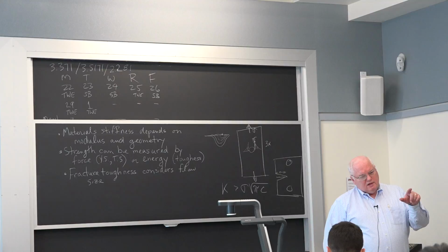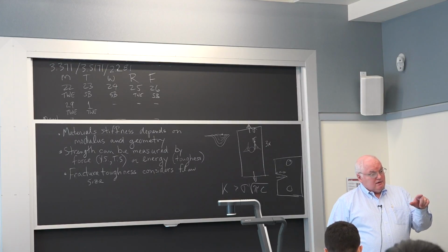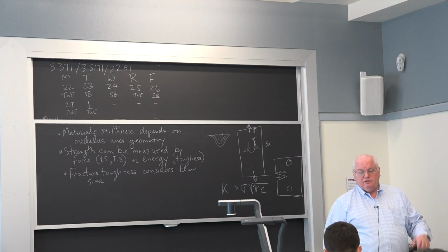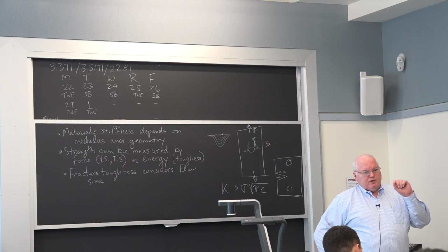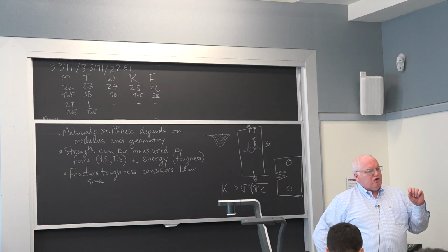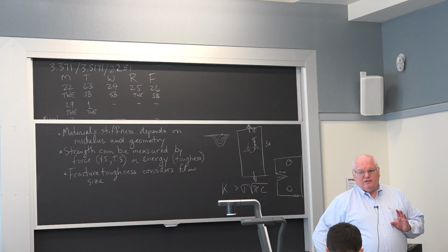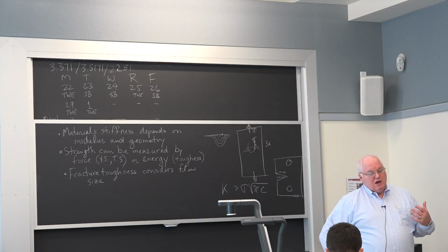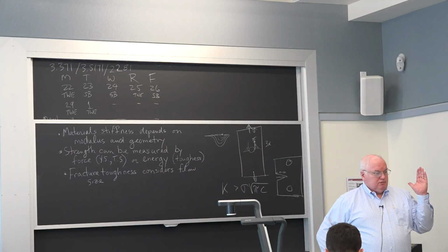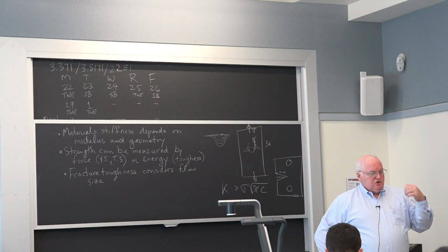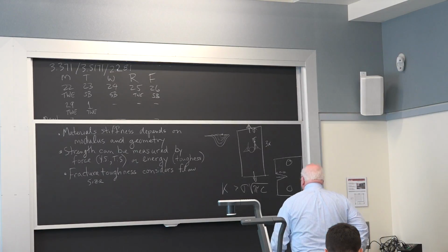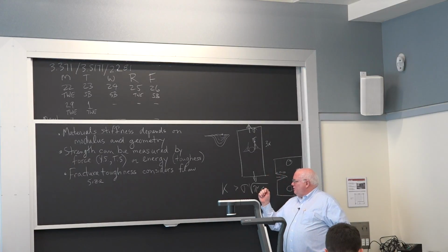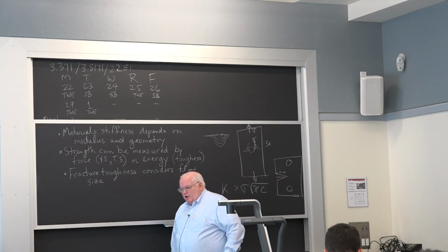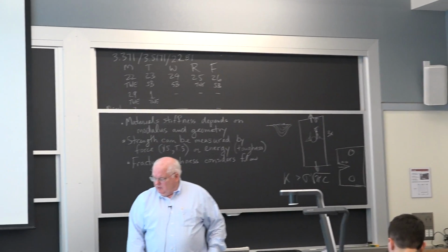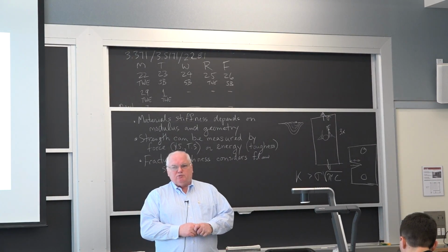And he found out, well, they already knew granite is a three-phase material. You can see white, black, and gray, 3 different crystal structures of 3 different minerals in granite. And what he found is that at the tip of the crack, you actually get little micro cracks. And those micro cracks absorb more energy than anyone ever thought they would in terms of fracture behavior. And that's why the Egyptians were able to raise that obelisk up. There was more fracture toughness. You could postulate some flaw size, calculate the stress, and estimate the fracture toughness, but the dynamic fracture toughness was greater than they had assumed. You only have 3 parameters here: applied stress, toughness of the material, and size of the flaw. And that's the science of fracture mechanics. Now, there's lots of different mathematics that goes with it, but fracture mechanics could explain these things.